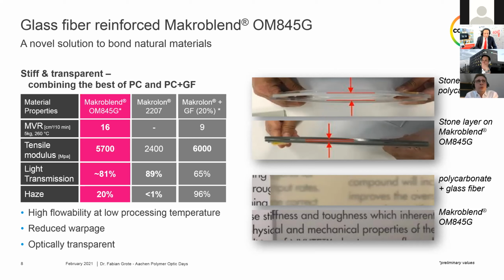However, when you use glass fiber material, typically you have the issue of poor optical quality. So it's a tendency to turn yellow, very hazy. And that's what you see on the third image from the top. So polycarbonate with glass fiber filled.